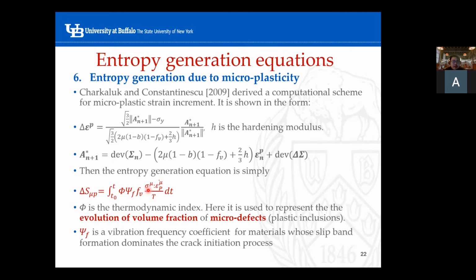This equation has a micro stress tensor product with microplastic strain, micro stress times microplastic strain. That will be the microplastic work divided by the temperature, work divided by temperature. That will be the entropy per unit time, times FV, which is the volume fraction of the micro defects.